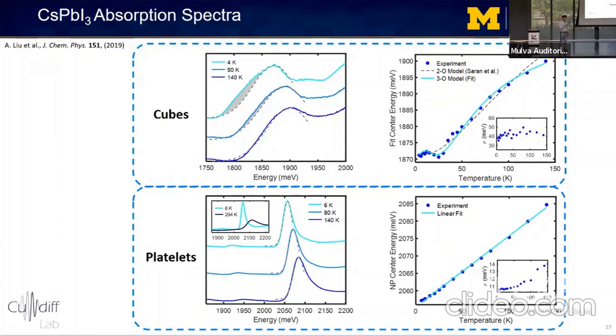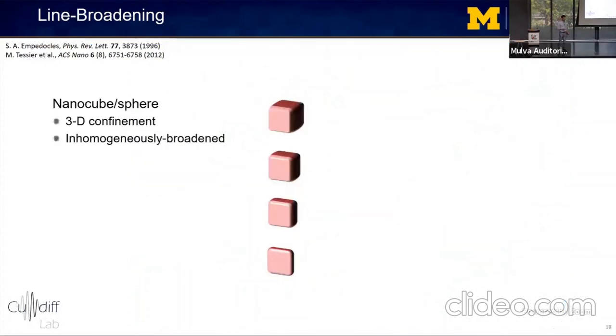And there's actually more action with the peak widths, which decrease with temperature until saturating at around 30 or 40 Kelvin. So this indicates that the absorption line widths at least partially reflect the actual exciton line shapes rather than just the inhomogeneous line width of the ensemble. So why is the disorder so different between these two nanocrystal geometries?